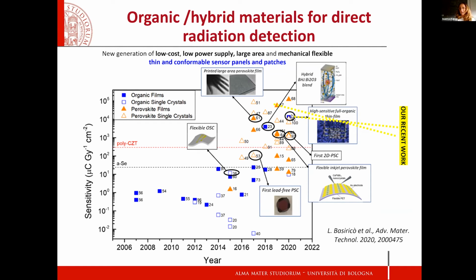They're both very interesting, as you can imagine. Single crystals can be grown in thicker dimensions, larger volumes that allow a better absorption of the radiation because it's hard to stop high energy photons, but it's also harder to scale them to large areas. So there are pros and cons with single crystals or thin films. Today I will focus more on the thin films, but there are very good results also on the single crystal form. Another important message is these two dotted lines, the red and the black one, that represent the state-of-the-art